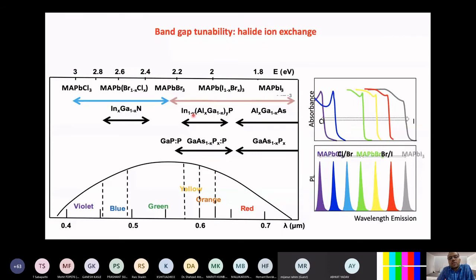Same thing if you put gallium, aluminum, indium, then this is the band gap range. If you have gallium nitride, you can get the band gap close to violet color. But if you add indium, which is bigger in size, by replacing the gallium, 1 minus X, you can get the green color emission from the gallium nitride semiconductor. So these are the recipes which were known to us from the inorganic semiconductors, whether it's the gallium phosphide family, gallium arsenide family, or gallium nitride semiconductor family. So we use that kind of knowledge in our background, and we use it on perovskite.